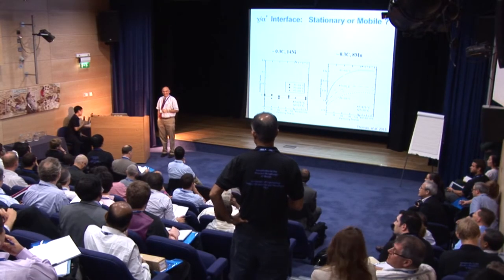Okay, thank you. We have a question from the rest of the world. Tata Steel from Netherlands, they have a question. Okay. The question is, if the intercritical annealing temperature has been done in, say, 800 to 900, is it possible for the manganese to partition in, say, 100 seconds? That's the question. So are we talking about a medium manganese steel? I guess so. So I guess it doesn't really matter. But I think there's some data in the recent literature that shows that you can get significant manganese partitioning at intercritical temperatures in relatively short times.